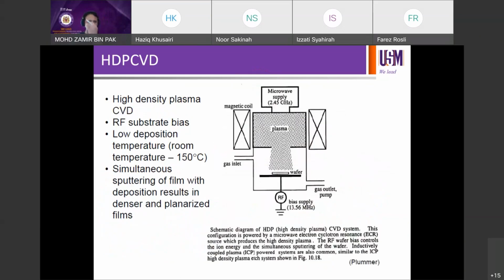So when you have plasma, you have low temperature, and you can then regulate or optimize these two parameters in order to produce the intended properties of your deposited layer. The plasma will enhance the decomposition mechanism of the incoming gas, silane in this case, and you have an option to reduce temperature, which you don't have if you don't have plasma. You have to run at high temperature, in the region of 1000 degrees C plus minus, in order to initiate the decomposition. So this is another one, high density plasma.